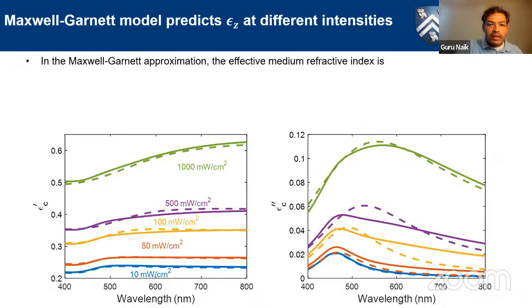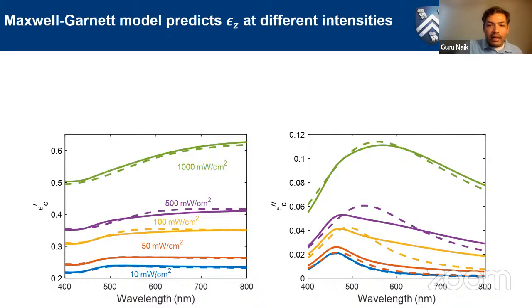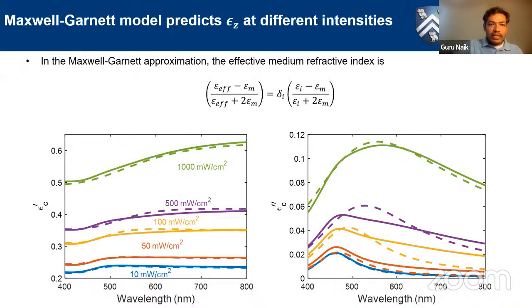So what we do is we assume that there are two different epsilons, or two different permittivity functions, for the two different stackings. And then we assume this Maxwell-Garnett equation, and for a given fill fraction, find out what this effective epsilon is. So that's how we come up with the effective dielectric permittivity. Okay, so this fit looks good. Of course, this is for just normal incidence, or one particular angle.